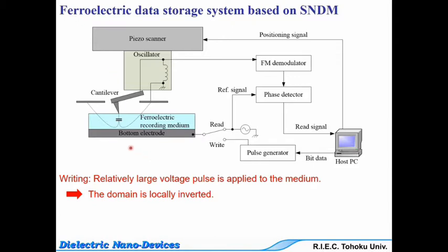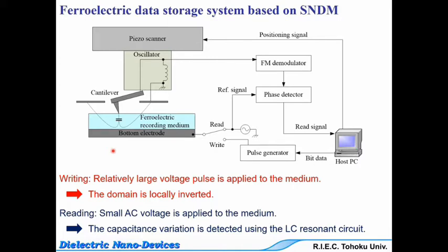The ferroelectric medium is on a linear piezo scanner. When we write the domain dot, or domain information, we apply a relatively large voltage pulse to the ferroelectric recording medium to invert the domain dot locally. And when we read the formed domain dot, we simply use the SNDM technique.